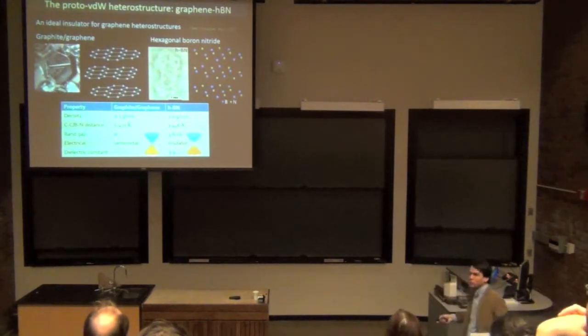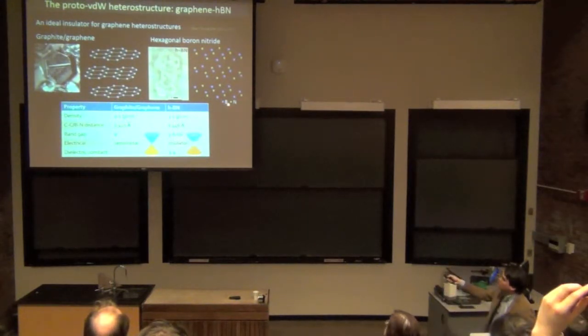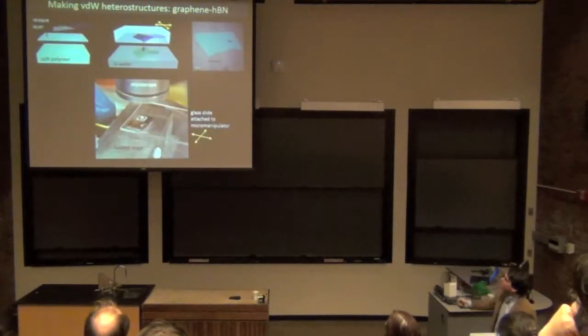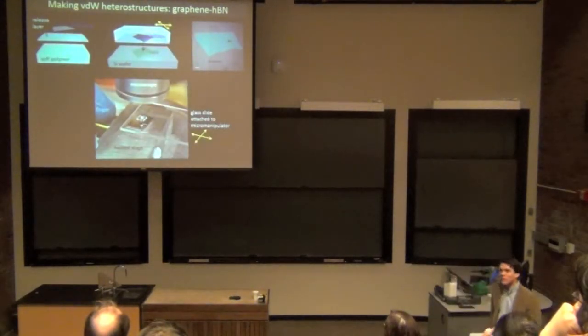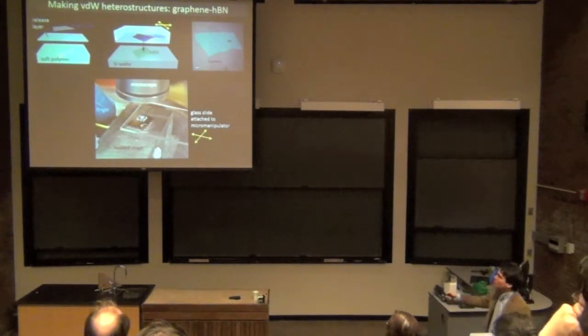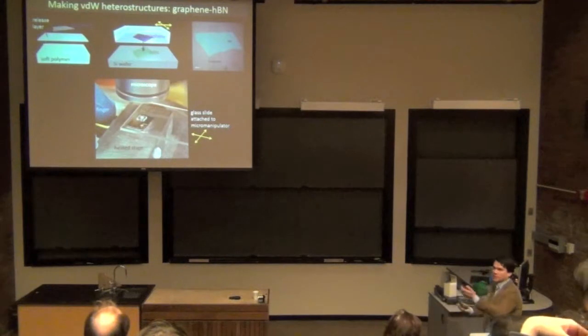But as I pointed out, the main difference is that graphene is a very good metal, or a very good semi-metal, and the hexagonal boron nitride, because of this difference in boron and nitrogen atoms, actually turns out to be a very good insulator. Okay, so how do we actually make these things? The way that we make them is almost embarrassingly simple. We start off with a transparent layer. So this is a soft polymer and then a release layer, which is basically a sacrificial layer.